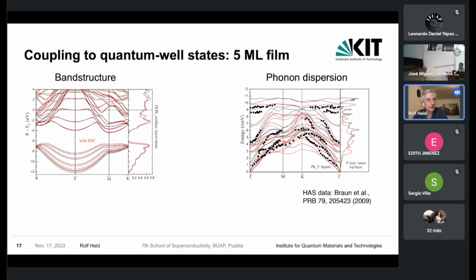Now, the second calculation shown here is the phonon dispersion for these 5 monolayer films. Again, there are 2 plots, one with spin-orbit and one without spin-orbit coupling, and the ones with spin-orbit coupling are the red ones. These are compared with experimental data, namely these phonons of such very thin films can be measured with the so-called helium atom scattering technique, which is a very sensitive technique to detect and analyze the vibrational properties at surfaces. And here you can see several phonon branches related to this film.